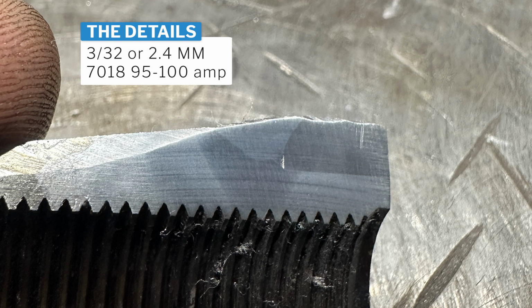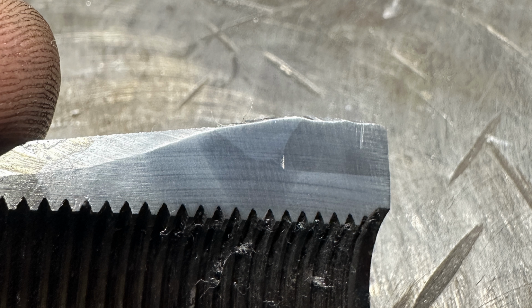Up first, we have the 3/32 7018 at 100 amps, and the overall weld profile looks like every other 7018 cut and etch. Generally speaking, really good sidewall fusion, not the greatest depth of penetration, and this is no exception. We have a little bit of a lack of fusion there where the angled part of the thread insert meets the quarter wall tube, and that's going to be very typical of all welding processes, so don't be surprised when you see that in other pictures in this video. But this is about what you're going to expect.